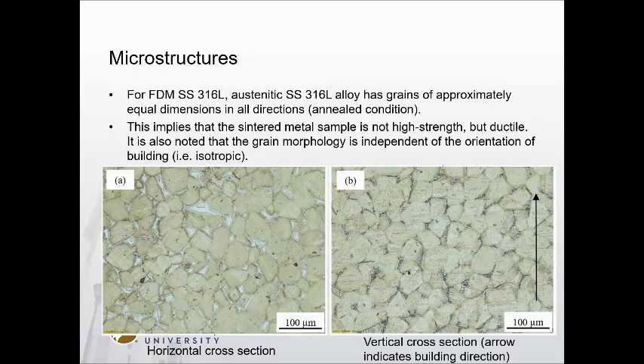So different from the selective laser melting process, which has the melt pool shape, for the FDM-based stainless steel 316, you can see there's no layer along the vertical building direction. Now this implies that the sintered sample is not high strength because of its microstructure, but it's ductile. Its grain morphology is independent of the orientation of the building. We can predict it is an isotropic material.